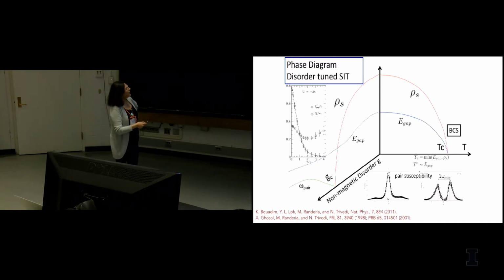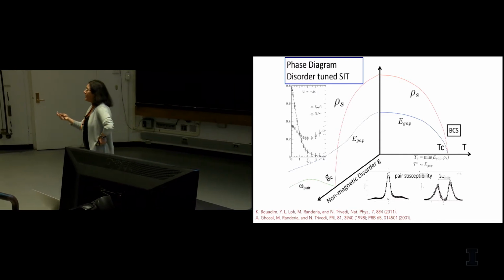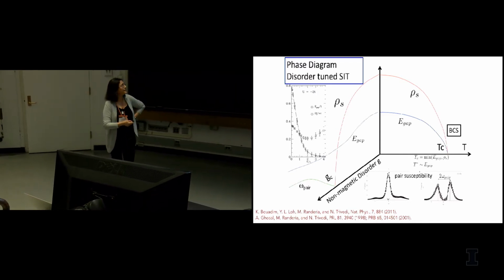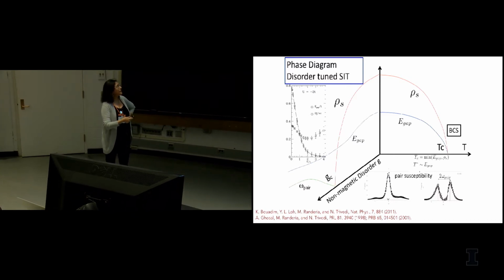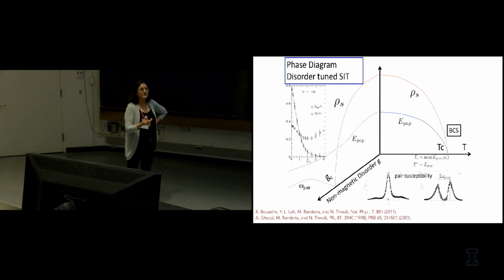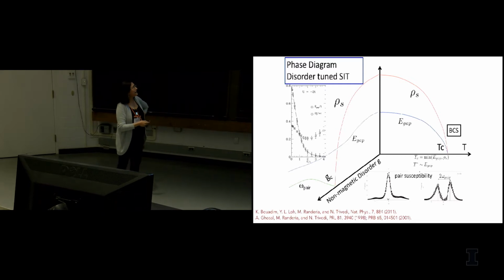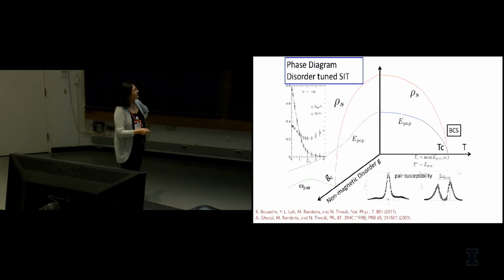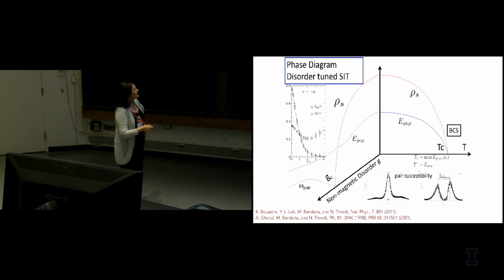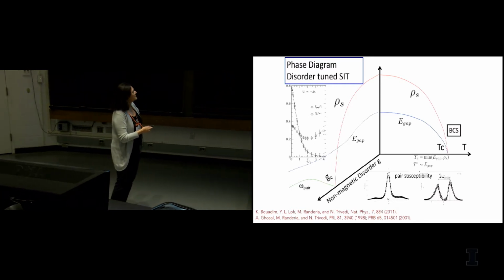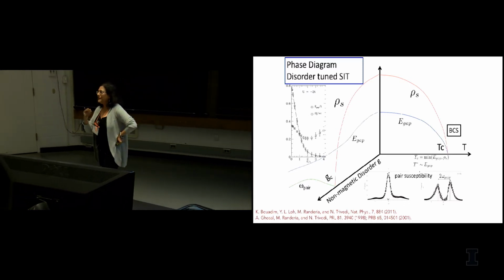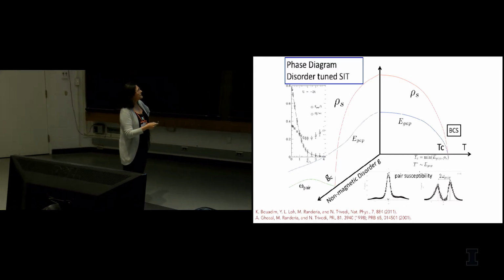Now you might ask, what happens beyond the critical point? Is there an energy scale that goes soft at that critical point? It's clearly not the single particle gap, which is continuing to remain finite. You have to go to the two-particle tunneling, or Josephson spectroscopy, where you try to inject a pair. And when you inject a pair in the superconductor, here, you can inject a pair at zero energy. That's the Josephson effect. This is numerical results. It looks like an experiment, but these are numerical results, and this width is coming from some analytic continuation that we have to do on the Monte Carlo.